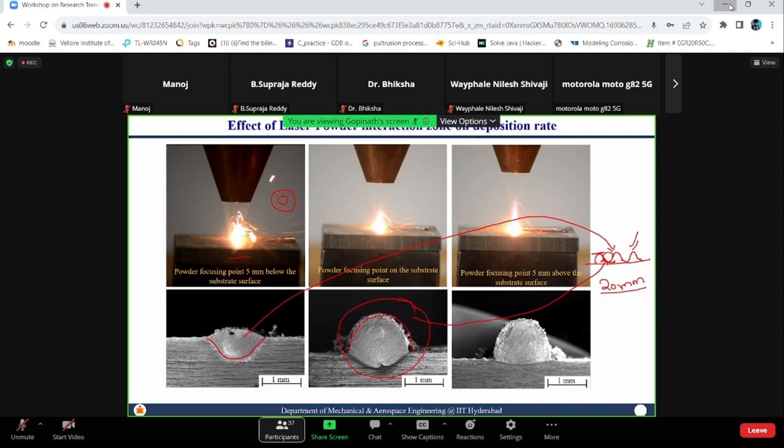So extreme high speed laser cladding or your regular cladding, by changing the process a bit, essentially what you are trying to do is work in this domain where most of the energy is being absorbed in your powder. Then the whole process can be shifted from additive manufacturing to extreme high-speed laser cladding. So this is a very thin coating. 650 micrometers was in our preliminary studies, but now we are able to deposit up to 30 micrometers.